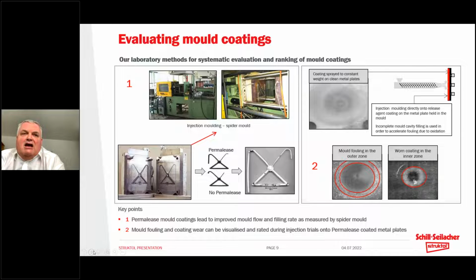It's a mold which has a quite extensive and uninterrupted flow path. It's designed here as an injection mold, although transfer versions are also available. And the idea is that you inject into the central part of the cavity, and then the mold flow continues around the flow paths, the so-called spiders, if you like, the legs of the spider, and we can measure the degree of mold flow achieved by that. What we do is to coat the clean mold with our mold release coating, and then inject into the mold.